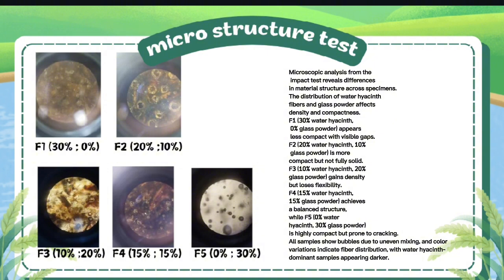Microscopic analysis test. Microscopic analysis from the impact test reveals differences in material structure across specimens. The distribution of water hyacinth fibers and glass powder affects density and compactness. F1, which is 30% water hyacinth and 0% glass powder, appears less compact with visible gaps. F2, 20% water hyacinth and 10% glass powder, is more compact but not fully solid. F3, 10% water hyacinth and 20% glass powder, gains density but loses flexibility. F4, 15% water hyacinth and 15% glass powder, achieves a balanced structure, while F5, 0% water hyacinth and 30% glass powder, is highly compact but prone to cracking.